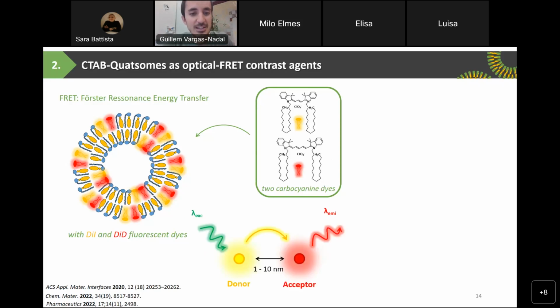And what is FRET? For FRET you need two dyes: one that will be excited, and then this dye will transfer this excitation to another dye, which is the acceptor, and we read the emission of this second dye. However, we need to accomplish two things in order to have FRET. First, the distance between the two dyes should be lower than 10 nanometers, and also the emission of the first dye must overlap with the absorption of the second dye, because if not, this energy transfer cannot occur. For example, if we increase the distance between the two dyes, then the FRET signal would be lost. So it is important that the two dyes are at a short distance in order to experience FRET.